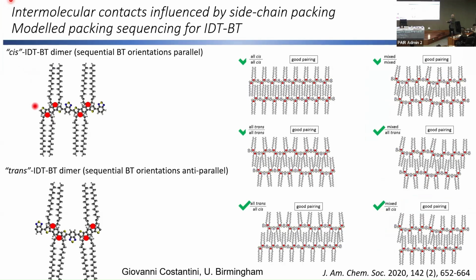So this is our IDTBT here, our unit here. This is our benzothiadiazole, and this is our indacenodithiophene. And because this unit is not regiosymmetric, depending on how these units orient along the backbone, they can have different conformations. So if we just look at one unit, one IDT, and this is a second unit. When we have the conformation where we have down, up, you can see that there's a spacing that's the same above and below the backbone.